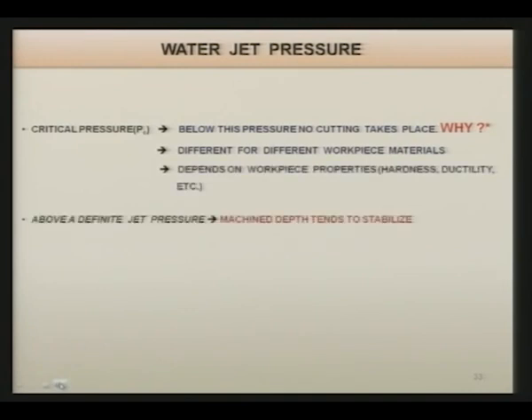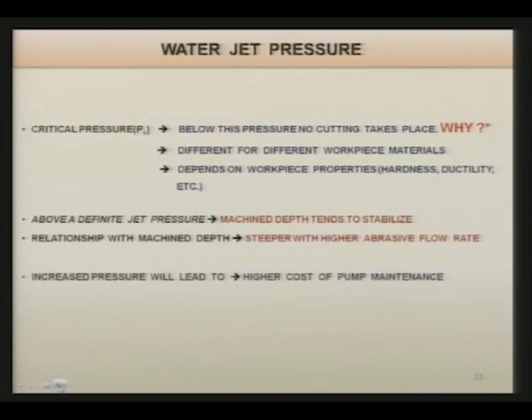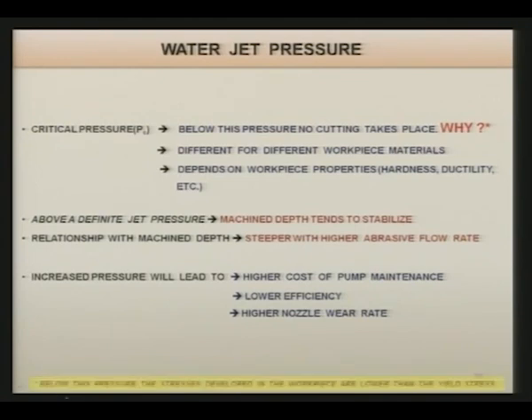The same thing is given here as the explanation: below the critical pressure no cutting takes place, and it is different for different workpiece materials, depending on workpiece properties. Above a definite jet pressure, machining depth tends to stabilize. The relationship with machining depth is steeper with higher abrasive flow rate. Increased pressure will lead to higher cost of pump maintenance, because if the pressure is very high, then maintenance of the pump becomes more expensive because of more wear and tear. It gives lower efficiency at very high pressure. Higher nozzle wear rate is also observed with very high pressure. Below the critical pressure, the stresses developed in the workpiece are lower than the yield stress. That is why you do not get any removal of the material.